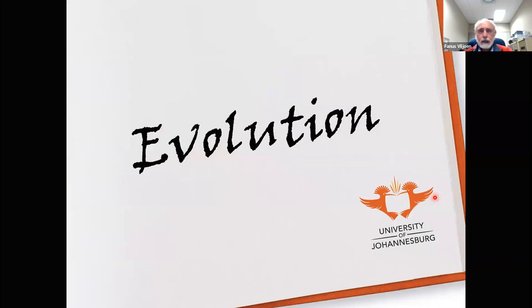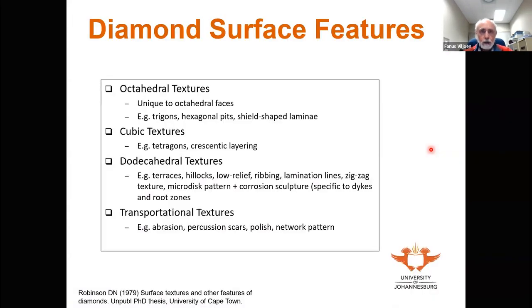Right, let's move on to the evolution of diamonds. And here I specifically want to talk about diamond surface features. If you look down the octahedral crystallographic direction of diamonds, you see very specific sets of surface features. For example, trigons, hexagonal pits, and shield-shaped laminae, which are unique to the octahedral direction.